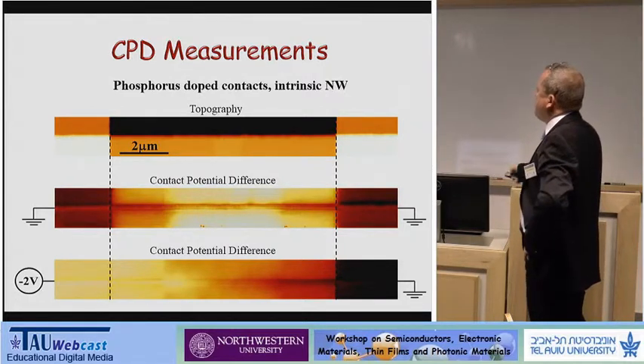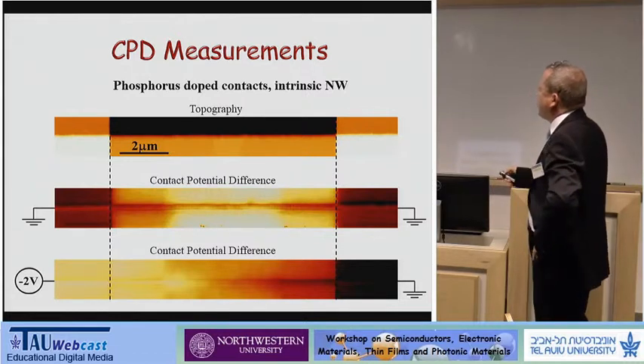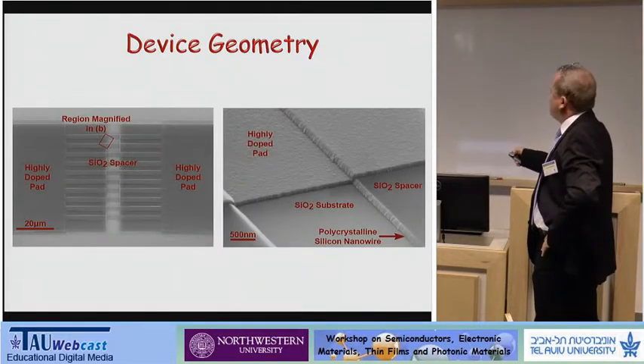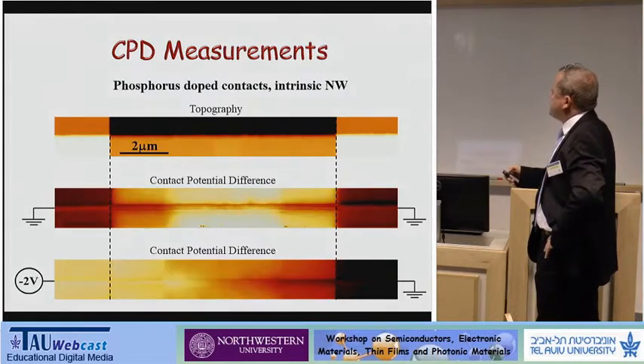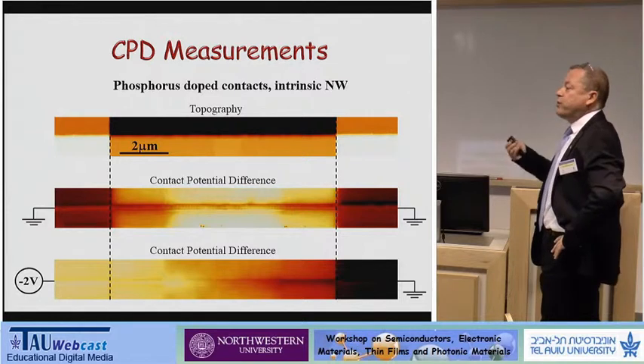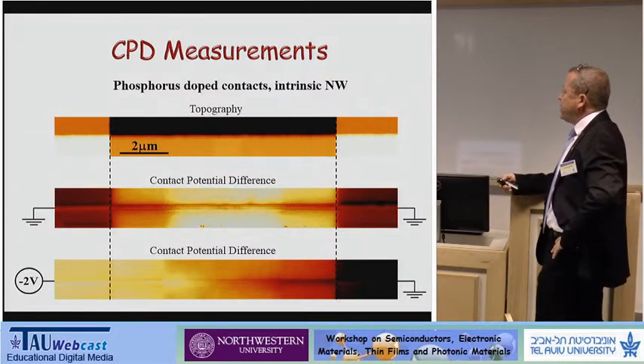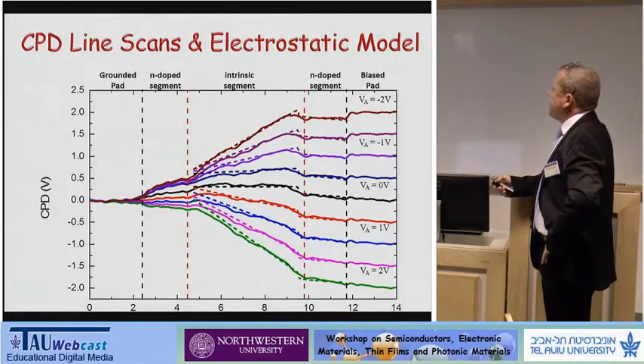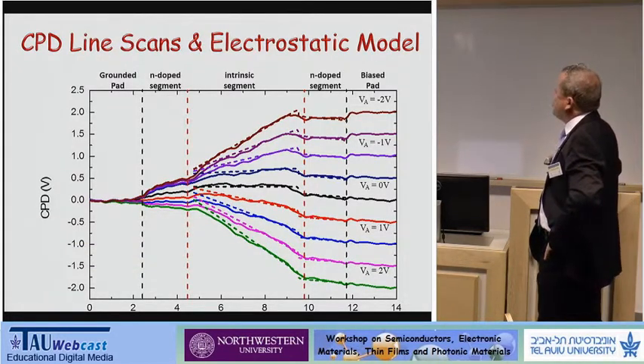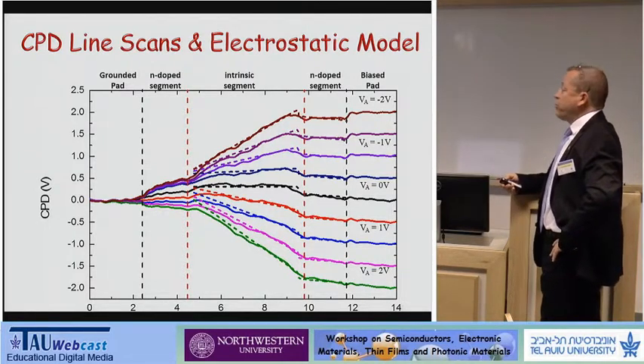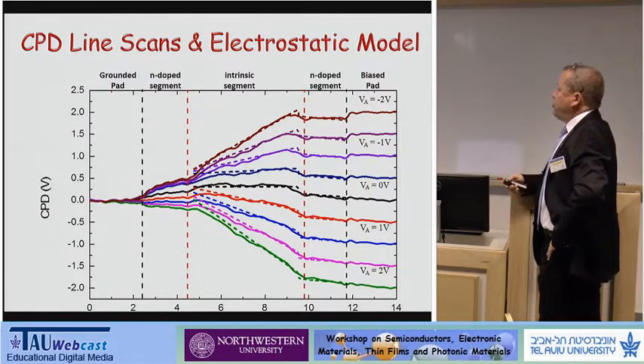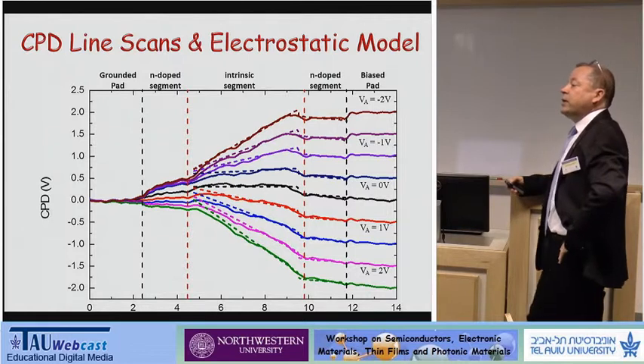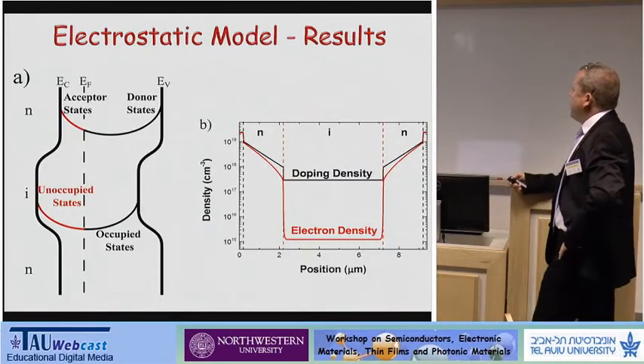And if you apply bias on the 2 sides of the nanowire, on the 2 contacts, you can gain important insight on the electrical properties of the nanowires. I will not go into all the details, but what we did was apply biases between the 2 pads, and we obtained the profile along the nanowire, and by fitting it to a solution of the Poisson equation, we were able to get the interface state density in the grain boundaries of these polysilicon grains.